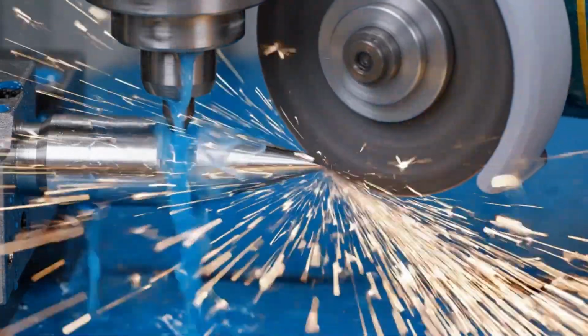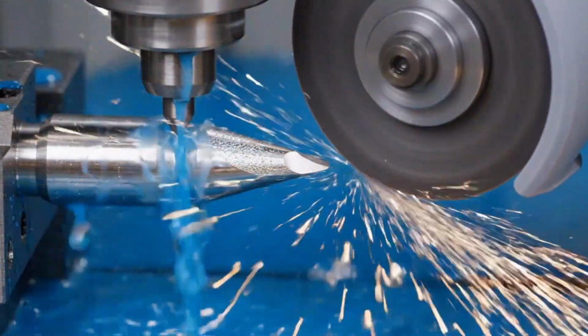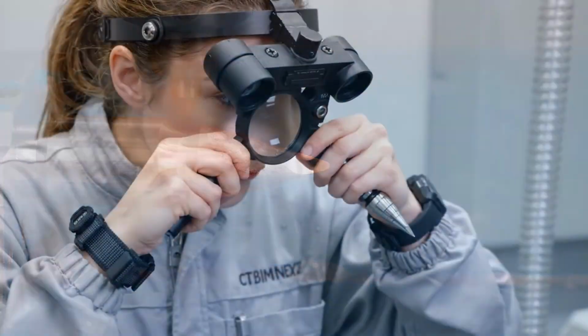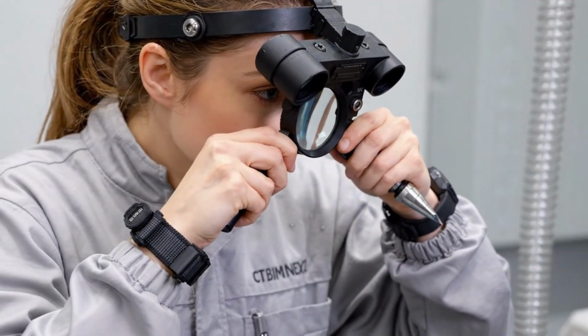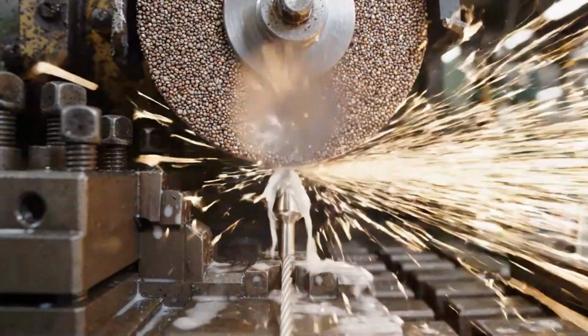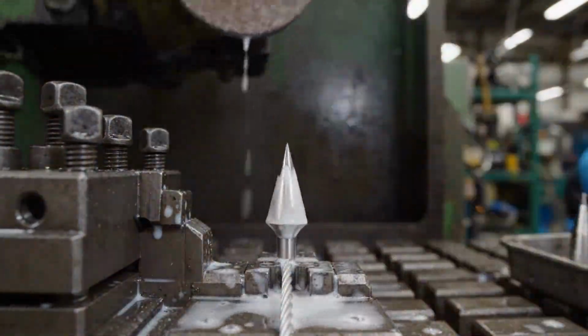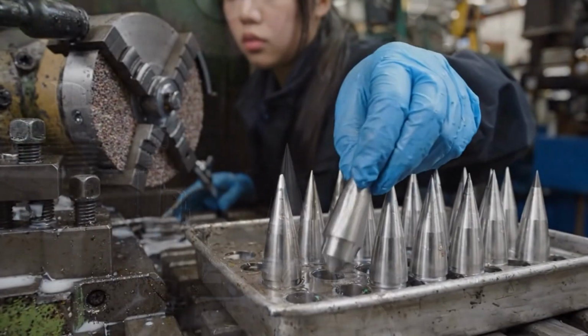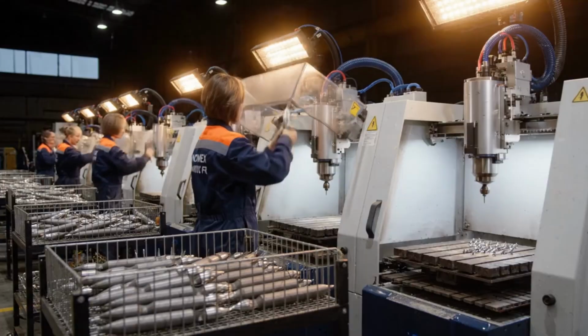The point is ground in a single clamping to eliminate concentricity error, and the tip and the shank are coaxial to within 2 microns. The cubic boron nitride wheel is dressed every 40 tips with a diamond tool that restores the profile within 5 microns.